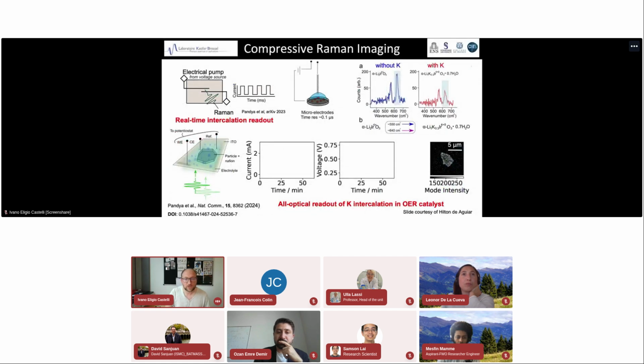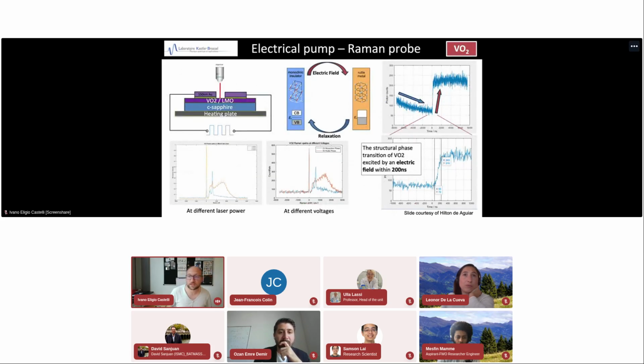Yes, of course, one of the techniques that we are using and that we believe is really powerful is the pump-probe. The Raman experiments, but also combined with pump-probe techniques, where we actually inject electrons into the system and look at how the system behaves. So going beyond just charging and discharging, we are forcing more electrons into the system, which is a unique technique that we can use in this case, and combining it again with different levels of simulation to have a one-to-one map between the two.